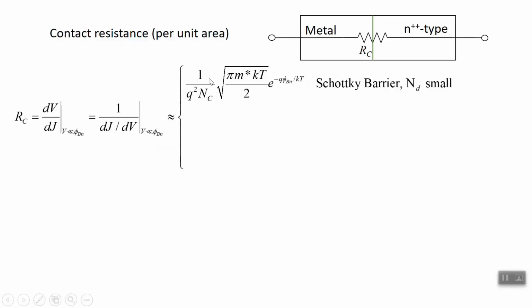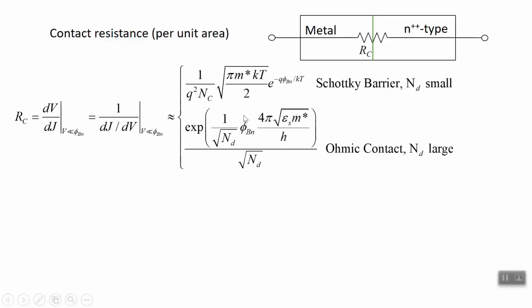And this is what it looks like for a Schottky barrier. That's a previous lecture. And this is what it looks like for the equation on the previous page. So you may need to go back to the lecture on Schottky barriers to see that this is what dV by dJ looks like, or rather 1 over dJ by dV in the limit that voltage goes to zero. And you can go right back to the expression on the previous slide to see what that 1 over dJ by dV at low voltage looks like. And that's the contact resistance for an ohmic contact. That is for a degenerately doped semiconductor, very heavily doped. As opposed to the contact resistance for a Schottky barrier, which you'll notice has this thermal activation in it. There's no thermal activation in this expression, and that's kind of a big difference.